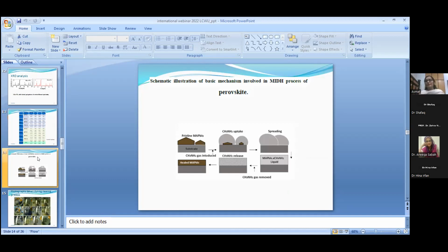We prepare the nanorods by the hydrothermal process, and at maximum we can get a length above 250 nanometer. But if you use pulse laser deposition or chemical vapor deposition, you can achieve a thickness of the titanium dioxide nanoparticles from 60 to 100 nanometer. And the second issue is the pore filling, because the pore filling is rather poor in the nanostructures, nanorods and nanotubes. So we involve a method called the methylamine defect healing process. Simply we call it a healing process, in order to improve the infiltration of the perovskite in the pores of the nanorods and nanotubes.